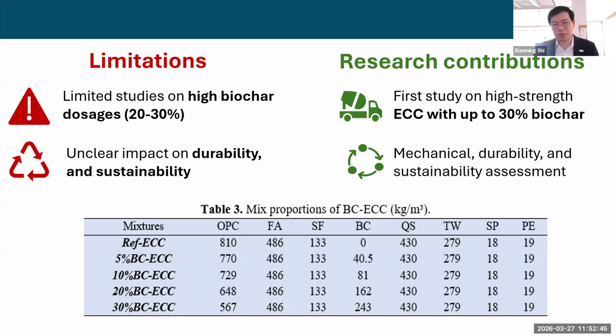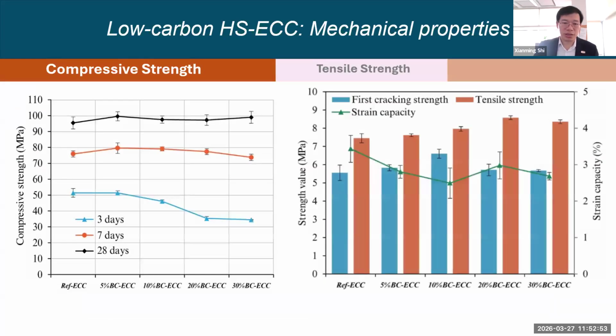People were thinking about 3% or less, but we're thinking, can we get to 30%? So the short answer is yes. You can see here 3-day compressive strength. You do see a significant reduction at 30%, but over time, once you get to 28 days, you're actually not seeing reduction. You're actually seeing a slight improvement of compressive strength. Similarly, in tensile strength, you're seeing a little bit of reduction, but that's okay. The tensile strength, at least at 20%, you're seeing much better. Even at 30%, you're seeing better tensile strength.